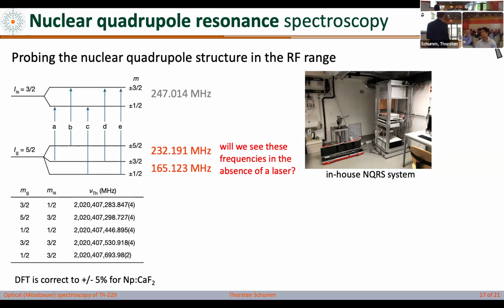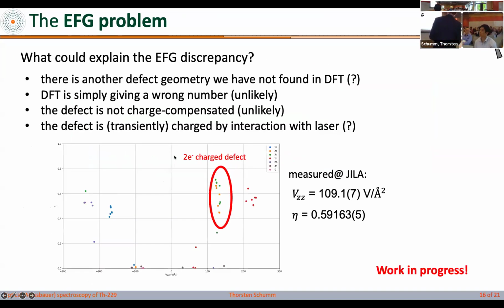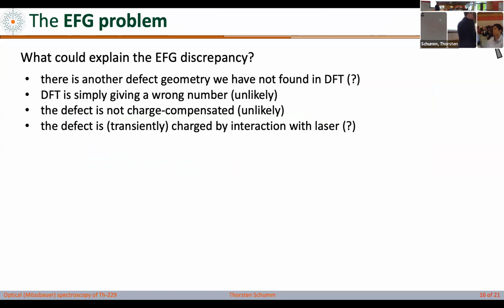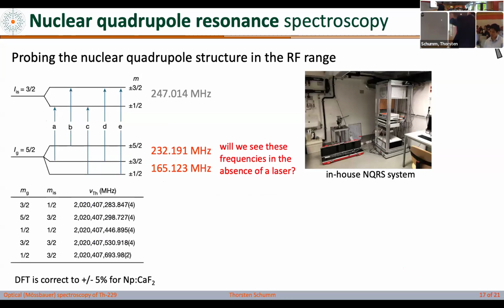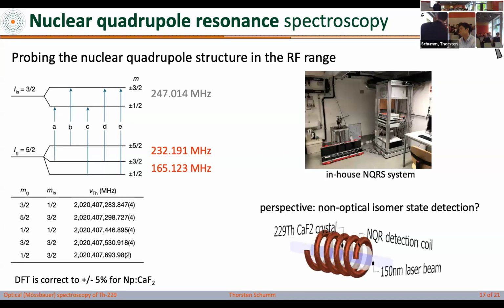If we don't, then maybe this charge state theory could be true, because then the energies wouldn't be here, as it's not charged when we don't have the laser. So we would have to find them somewhere else. Just because I'm jokingly dissing density functional theory, we did a test experiment with another nucleus, neptunium, doped into this calcium fluoride crystal, and their DFT was correct to within 5% error. So they usually know what they're doing. So something's wrong here, and we don't know yet.